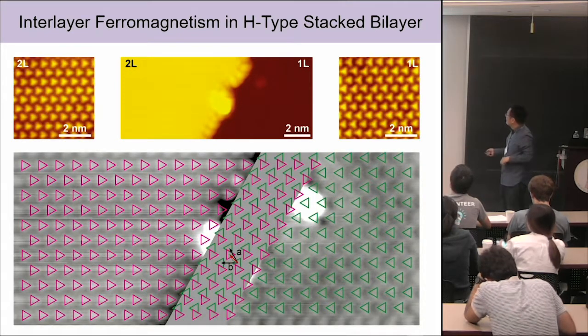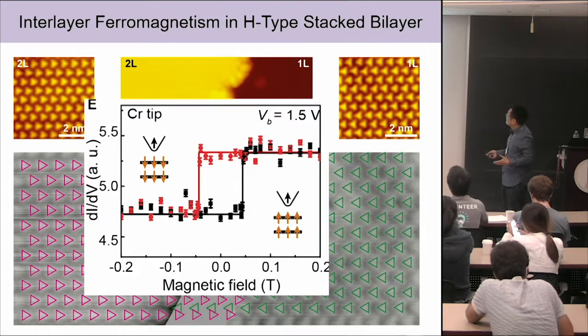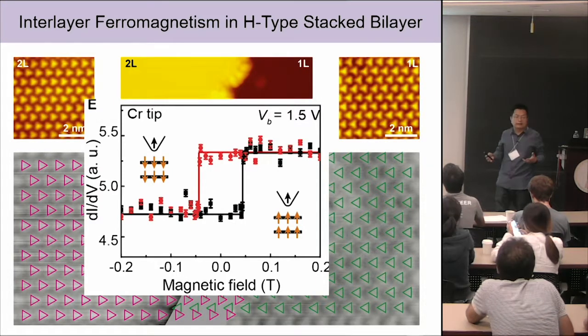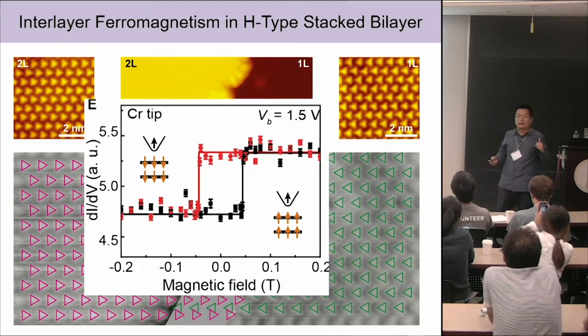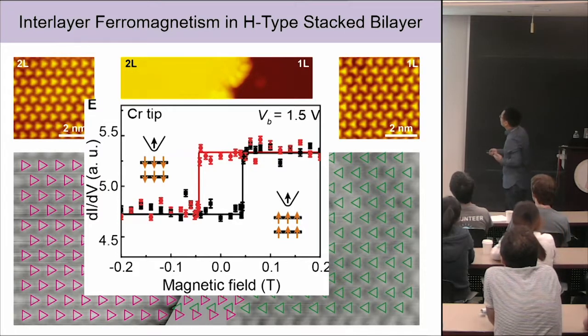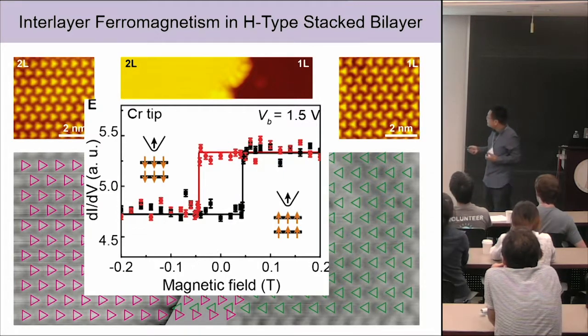What we found is actually it's H stacking. It's not the monoclinic rhombohedral R stacking I was talking about. So it's H stacking. And for the H stacking, indeed you have a ferromagnetism. That's the conclusion, okay?